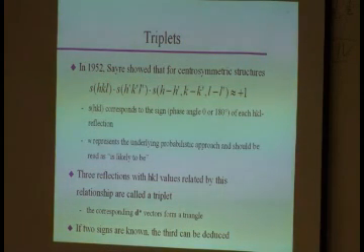This is what you call a triplet. Okay? And what he showed was that the sign, because it's really just a plus or minus sign, of the phase in a centrosymmetric structure, of the first reflection times the second times the third one is likely to be positive. Okay, so this sign here is a probability expression, so it should be read as "is likely to be," not really as approximate.